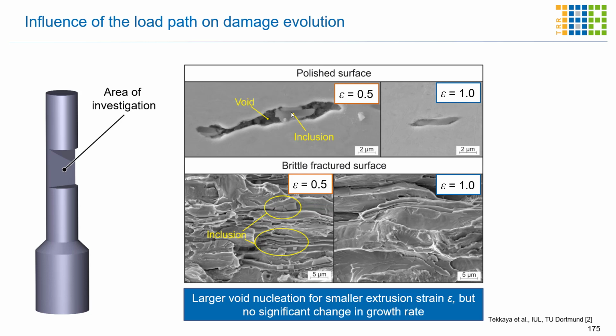environment, and in general also inclusions are included within such voids. So sometimes it's quite challenging to distinguish between a void and an actual inclusion. On the right hand side we also see some void, but this void is really small, and most of the void is filled with some inclusion.